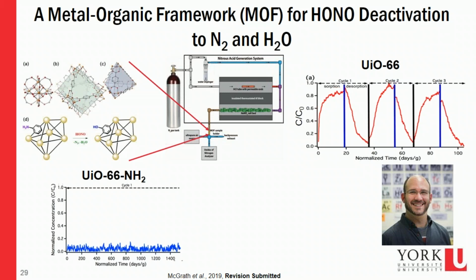But if you do some chemistry where you put an amine group on this particular linker, you can actually chemically scrub HONO from that gas stream. And so here I'm showing that same normalized concentration as a function of exposure time. MOF chemists like to use this normalized time in days per gram of MOF, so days of exposure at whatever concentration per gram of MOF. I'll just draw your attention to the fact that we went up to 100 here and did 3 sorption-desorption cycles, from a complete breakthrough down to a complete desorption.